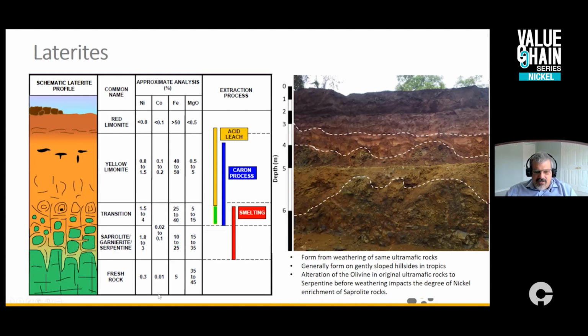So those rocks originally started with 0.3% nickel, 35 to 45% MgO. As we look at the weathering that happens, the weathering process is what upgrades the nickel from that 0.3 to grades that become mineable. So as we look at the fresh rock to the surface of the profile, those are the most weathered rocks, and that MgO content reduces down to virtually nothing. And so that removal of that material naturally upgrades the amount of nickel and iron that remain.